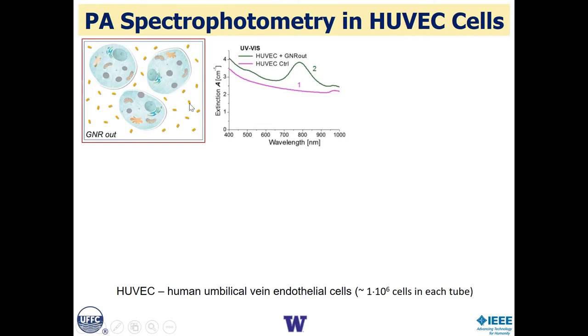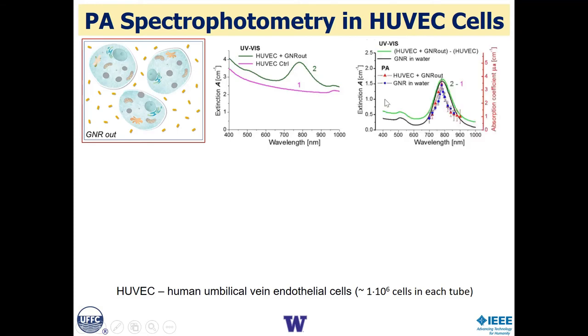So you have separated cells and nanoparticles. We make a subtraction measurement between the total solution and one with just cells but no nanoparticles. When we do the subtraction measurements, we get a reasonable spectrum. It looks like the nanoparticles. And underneath it, we have the measurements we made with this non-contact photoacoustic system, and they're very, very similar. So you should be looking at me now and saying, Matt, why do you do this? You said you get in trouble, yet you just showed the photoacoustic and the simple subtraction measurements look the same. Yeah, that's in the simple case.